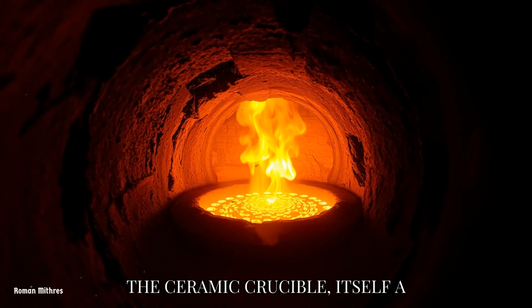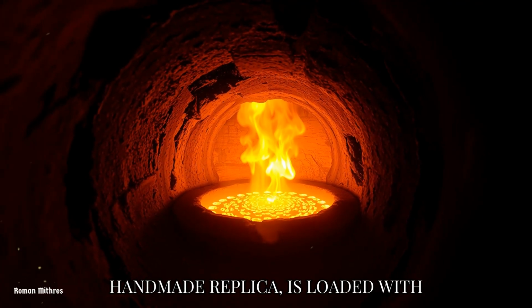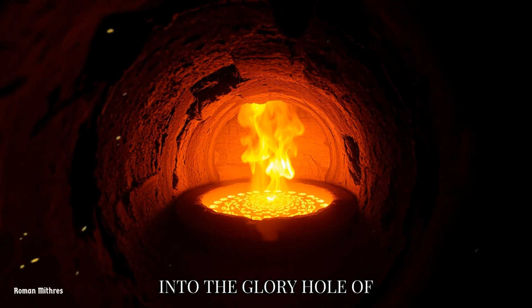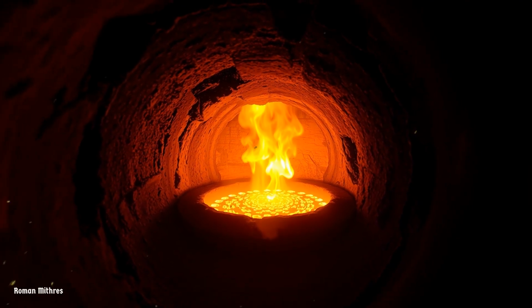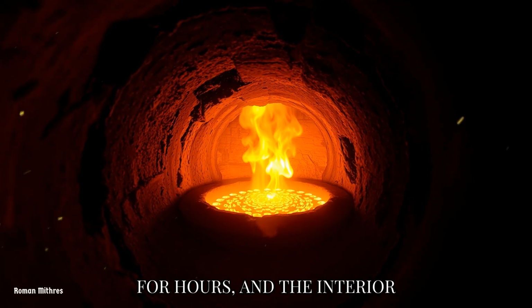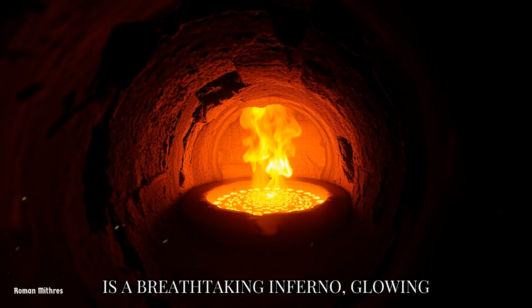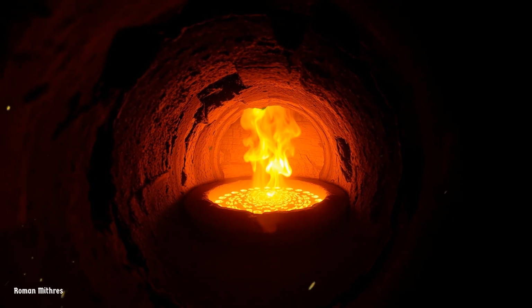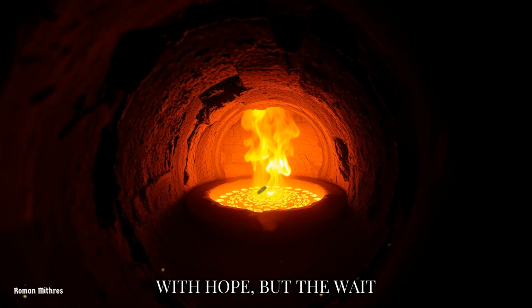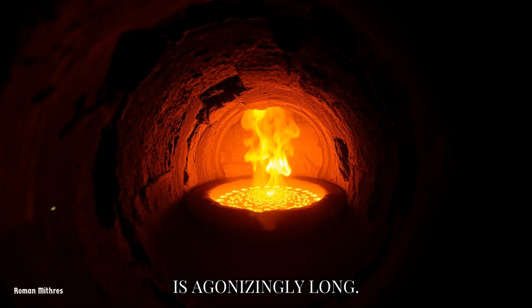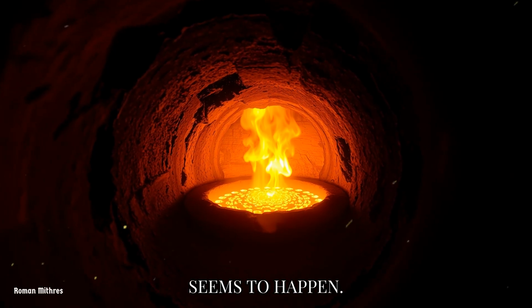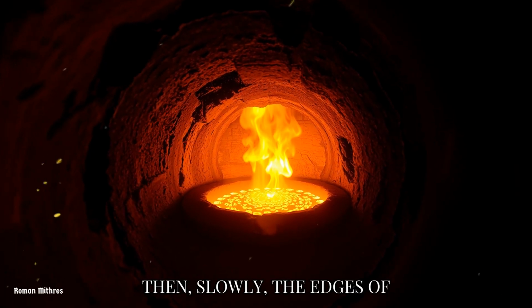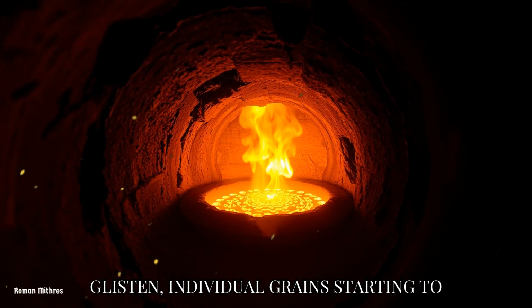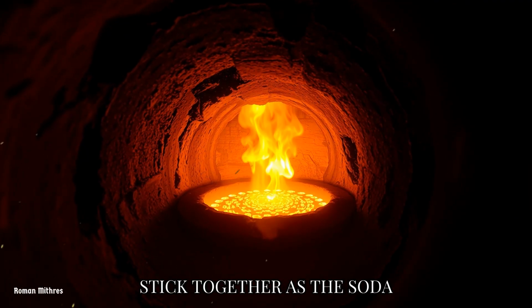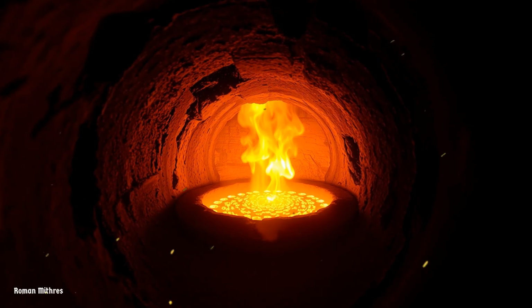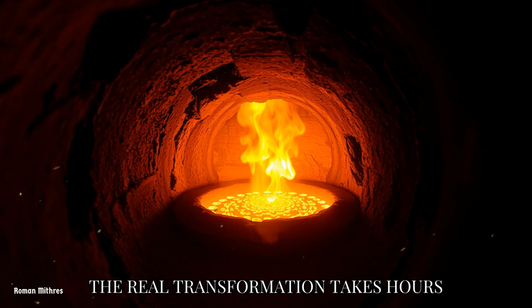The ceramic crucible, itself a handmade replica, is loaded with the material and carefully placed into the glory hole of the now roaring furnace. The fire has been stoked for hours, and the interior is a breathtaking inferno, glowing with a fierce orange-white light. The initial moments are filled with hope, but the wait is agonizingly long. For the first hour, nothing seems to happen. Then, slowly, the edges of the fritted powder begin to glisten, individual grains starting to stick together as the soda works its corrosive magic. The real transformation takes hours more.